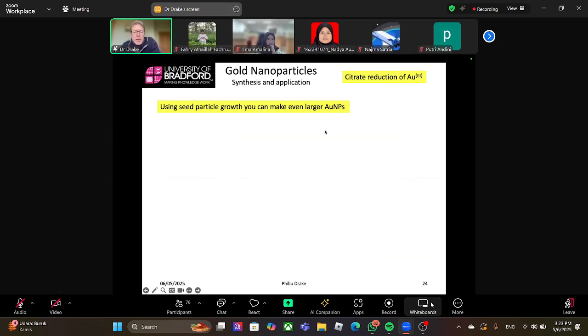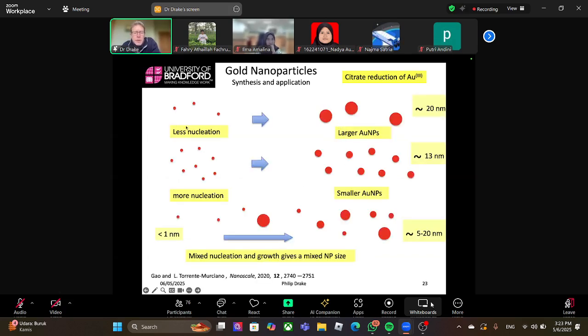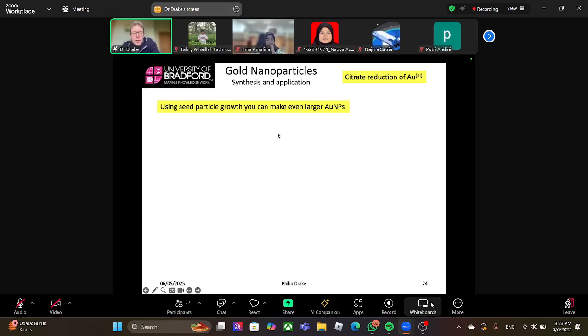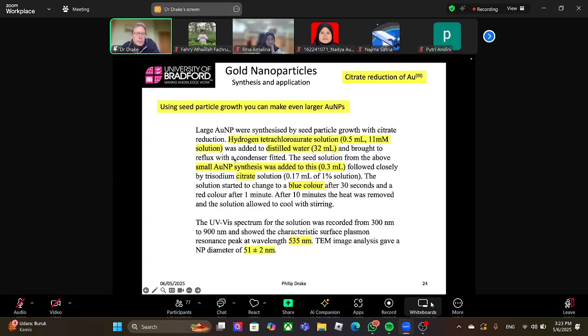We can even make larger particles. Using the Turkevich method, the biggest particles you can make are about 20 nanometers. No matter what you do, you're going to get the red particles about 20 nanometers in size. To make bigger particles, you need a different method. You use seed particle growth.